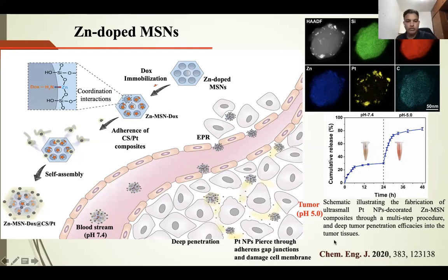So here this PT creates gaps inside, and then tries to damage the adherens gap junctions between the cells, so that the other nanoparticles behind can enter into the deep tumors, which we have confirmed through different characterizations. Probably this has been published in 2020 in CEJ. Impact is around 13 now.